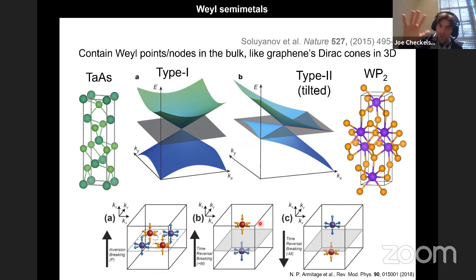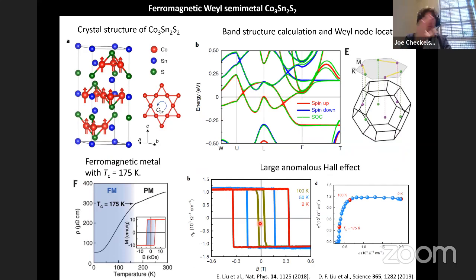So it took a little bit longer to find these magnetic variants, but the last one or two years have seen more and more examples of these so-called magnetic Weyl systems. This is just one particular example I particularly like. It's a material called cobalt tin sulfide. And what it does is it has these ferromagnetic layers. The magnetism may be a little more complicated than was originally thought, but nevertheless, it's a pretty good magnet. It magnetizes around 175 Kelvin, and has a nice magnetic hysteresis loop.